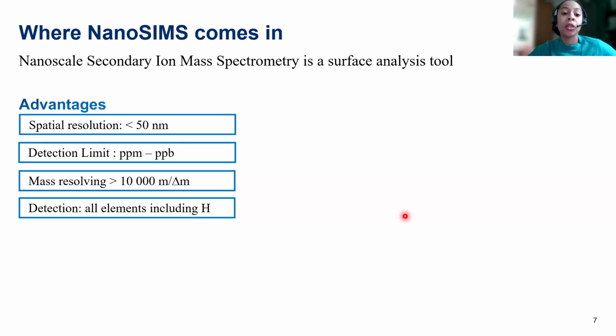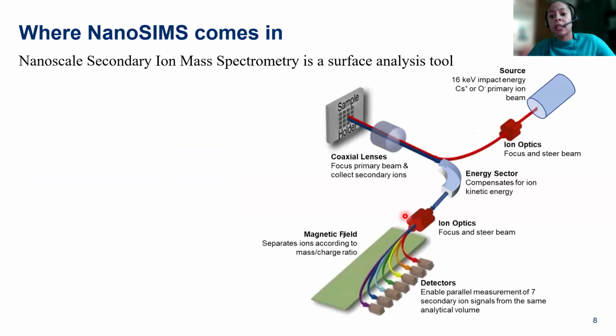Now, it is, of course, a lower throughput type of analysis. And since Cecile talked about NanoSIMS a bit last week, I won't go too much into detail about this, but we have a source, which is your cesium or oxygen primary beam, and we use some ion optics to direct the ion beam onto a sample where that energetic beam causes ionization, and then we can collect those secondary ions along the exact same optics, and then we pass it through another series of optics, and we separate these ions based on their mass to charge ratio.